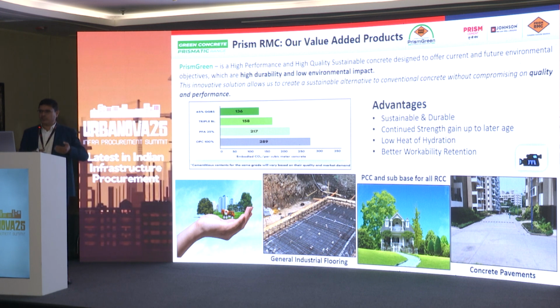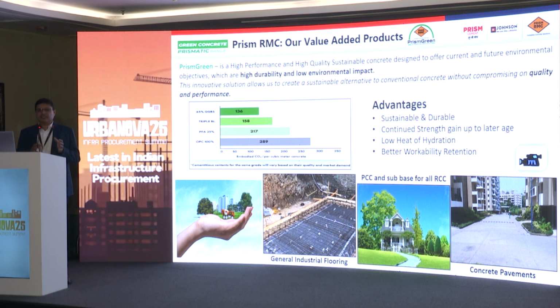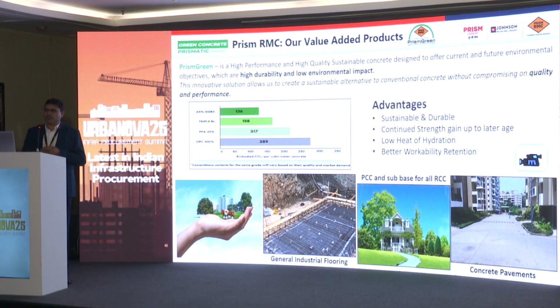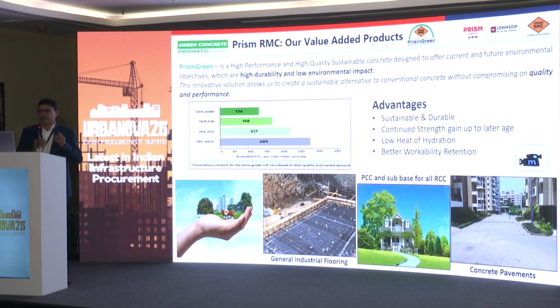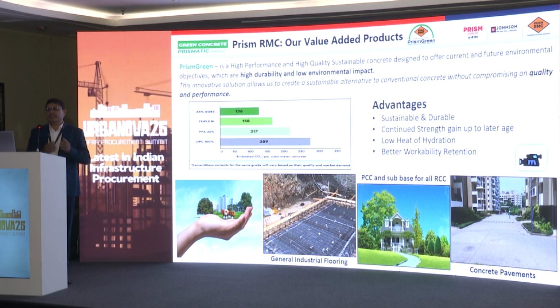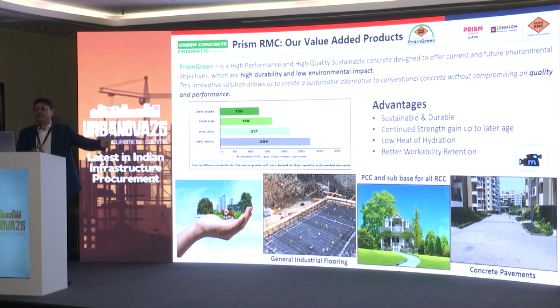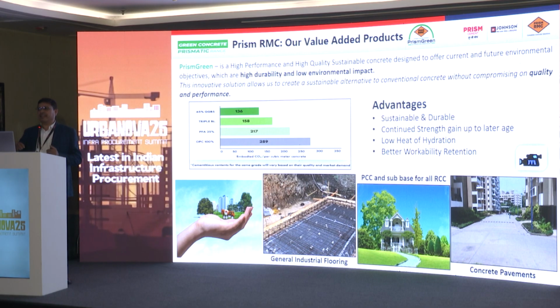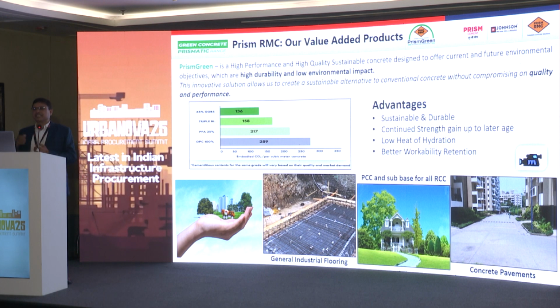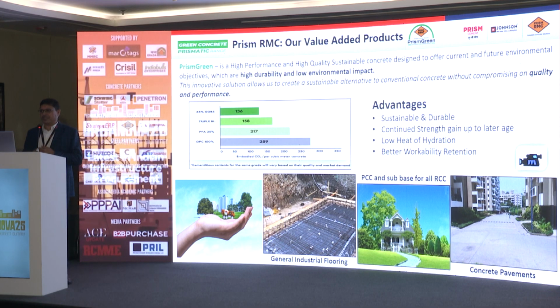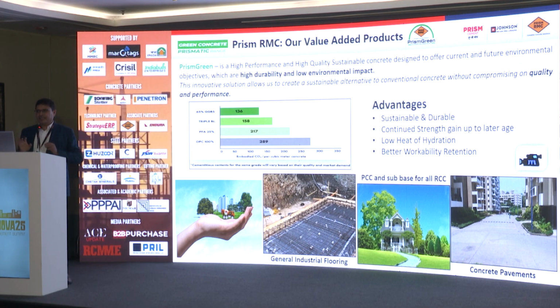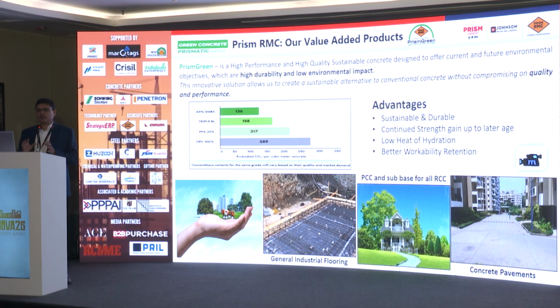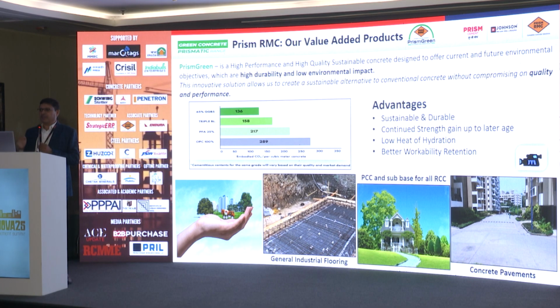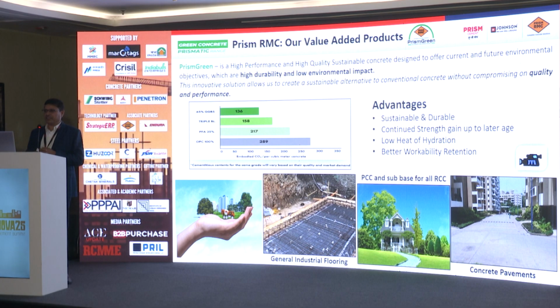It comes exactly in zone 1, but the challenge is that the specific gravity of copper slag is very high. The specific gravity of river sand is 2.65, while that of copper slag is around 3.8, so it is about 1.5 times heavier than natural sand. That's why we replace only up to 30%. The IS code allows replacement up to 35%, so we are using around 30 to 35% in the concrete.